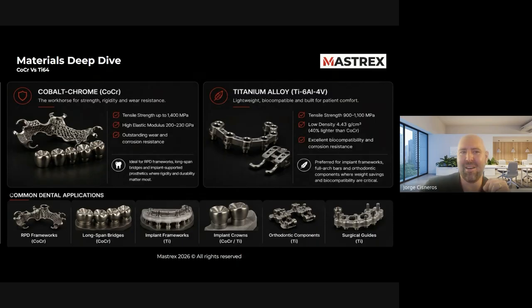As you can see, a lot of light weighting has been added to it. So there's a lot of lattice structure inside there, those thin lines. So that removes the material overall. It'll reduce the print time. It makes the part a little bit lighter, and it's something that couldn't really be done through traditional manufacturing. You couldn't really mill that or cast it. It wouldn't turn out very well. So those are some of the added benefits that you get from the metal additive or the laser powder bed printing.